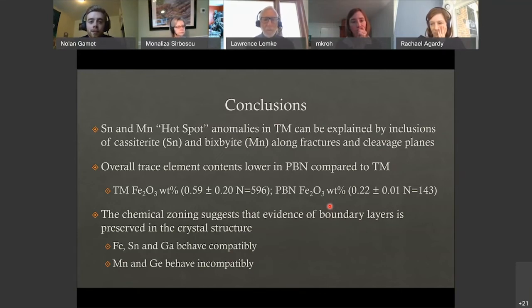And then we converted some of these weight percents into iron oxides, in which Tin Mountain revealed to have 0.6 with a standard deviation of 0.2, and PBN had an iron oxide weight percent content of around 0.2 with a standard deviation of 0.01, almost 3 times lower.